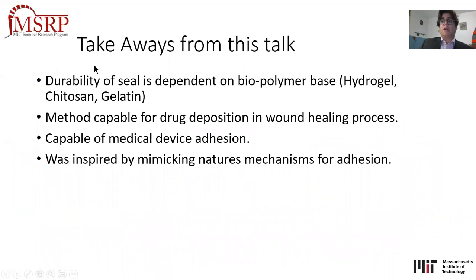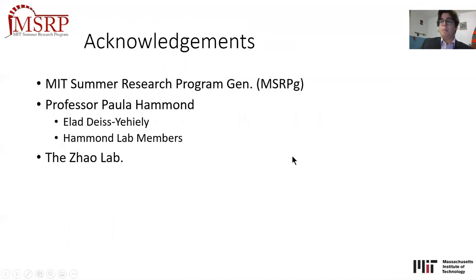Some takeaways of this article were that the durability of the seal is dependent on the biopolymer base, either hydrogel, chitosan, and gelatin, or their rearrangement of how they are combined. This method is capable of drug deposition in the wound healing process, and also capable of medical device adhesion. And one important factor was that it was inspired by nature's mechanisms for adhesion, such as the spider web.